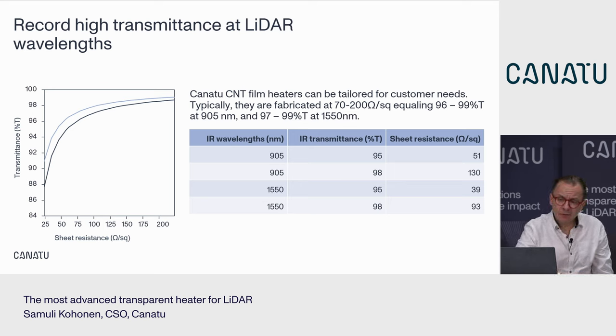If we are talking about the transmittance at LiDAR wavelengths, taking the example of a 905 nanometer LiDAR and a 130 ohms per square heater, which is also rather typical, we are able to meet roughly 98% substrate normalized transmittance. If we are talking about 1550 nanometer LiDARs, with 93 ohms per square heaters, we are able to meet 98% substrate normalized transmittance. And these curves on the left side illustrate the correlation between sheet resistance and transmittance.